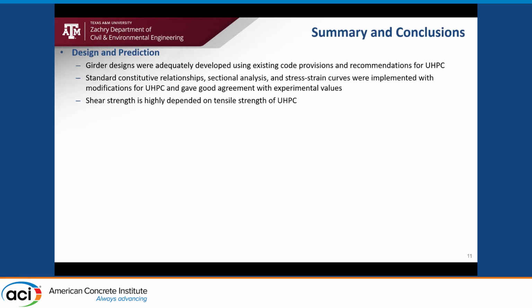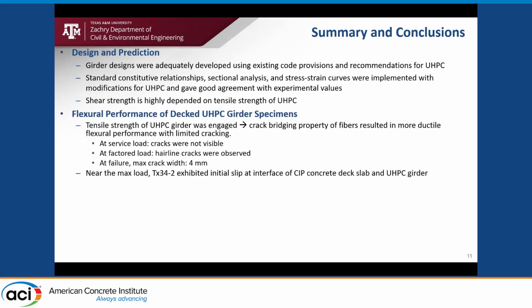From the experiments conducted, the following conclusions can be drawn. The girders can be designed for UHPC using the standard code provisions with slight modifications for UHPC. The first principles of mechanics hold good for identifying the behavior of UHPC girders with conventional concrete deck slabs. Using standard constitutive relationships, stress strain models, and a sectional analysis gave us good agreement with the predicted results and the experimental results. It was seen that the shear strength is highly dependent on the tensile strength of UHPC from the experimental results. The flexure performance was kind of governed by the composite action with the conventional concrete deck slab on the top and the UHPC girder being mainly engaged in tensile strength at the bottom.